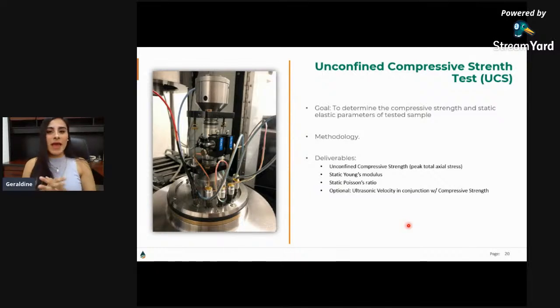Okay. Well, now the first compressive strength test is UCS. It's the most common one. The goal of this test is to determine the compressive strength of the rock and the static elastic parameters of the sample tested. It consists of applying an axial load to the sample until the sample fails. With this test, you can get the total peak of axial stress when the sample fails, the static Young's modulus, the static Poisson ratio, and optionally, you can run acoustic velocity in conjunction with this test.